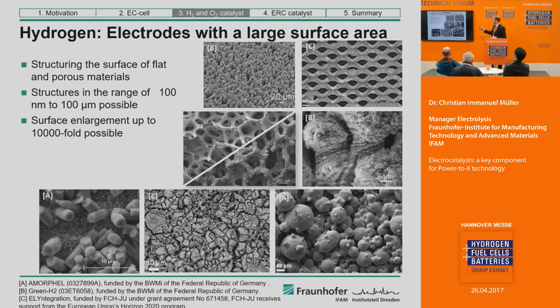So we are able to produce different structures in the range of 100 nanometers to 100 micrometers, and we get roughened surfaces. And these roughened surfaces have a much larger surface area. And we can structure different surfaces, for example, flat surfaces, or we can structure these expanded meshes. We can use foams, you see here, which can also be produced at our facility, and we can also modify these foams.